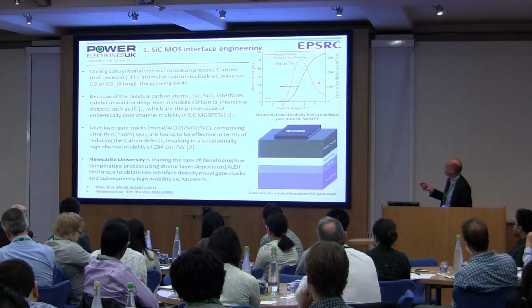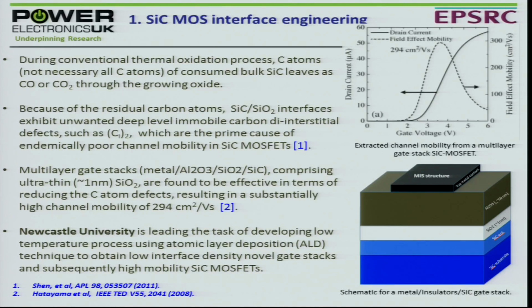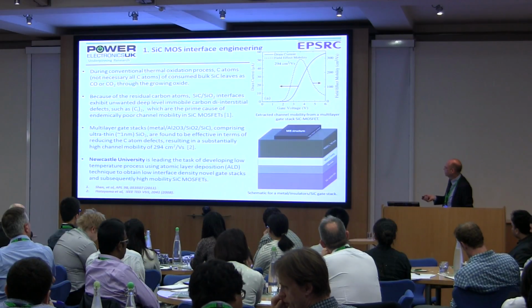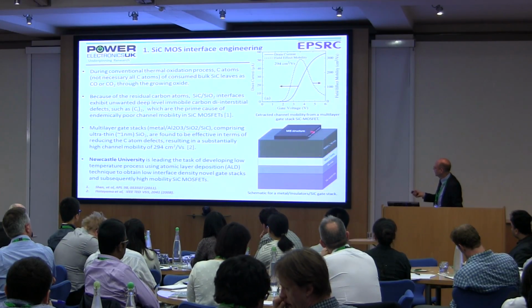dielectric, and the literature seems to point at, this is taken from the literature, that you get extremely high mobilities. Remember, we had about 20. The peak mobility here is over 300. We've not seen that yet, but that's what is promised using this technique. So we're supplying some epi layers to Newcastle, and they're building these structures on top. They have some unique processing capabilities to deposit this material. It's not to scale that.